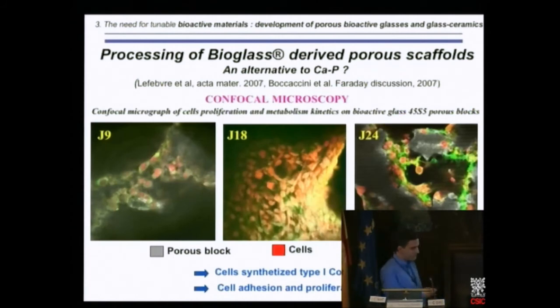These are images taken by confocal microscopy, so you can see in depth inside the porous substitutes by optical microscopy. And these are confocal micrographs of cell proliferation and also metabolism kinetics on bioactive glass porous blocks. So here is the surface of a pore. After 9 days in simulated body fluid or cell cultures, the cells are proliferating inside the bone substitutes. The cells are in red, and with time you have an increase of the proliferation of the cells inside the bone substitutes. And what is maybe more important is that the cells are able to produce type 1 collagen.